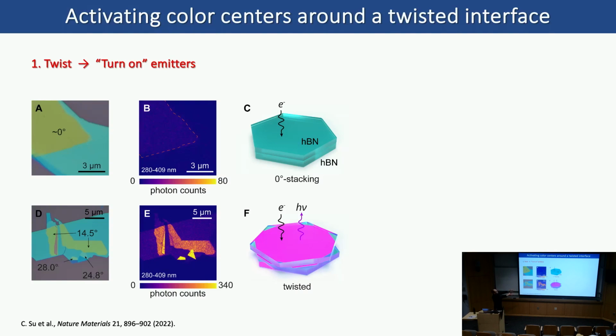What we found was that by twisting bilayer hBN, at the twisted interface, you can see there are some UV emitters getting activated. If you compare that with a 0-degree stacking, which doesn't have any twist, these, B and E, form a panchromatic photon count map, which shows that at the untwisted interface it doesn't really have any increase in emission. But whenever you have a twist, there's something that emits. It becomes really bright.